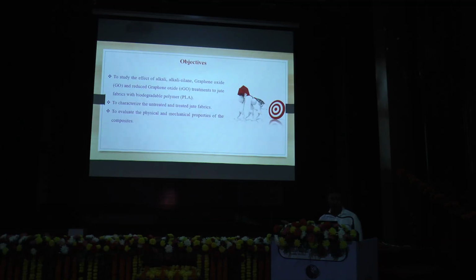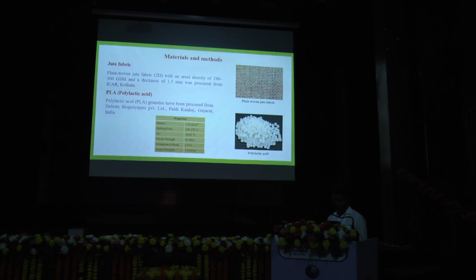PLA pellets, then graphene oxide also, and reduced graphene oxide treatment to the jute fabric. To characterize the untreated and treated fabrics, then to evaluate the physical and mechanical properties of the composite.